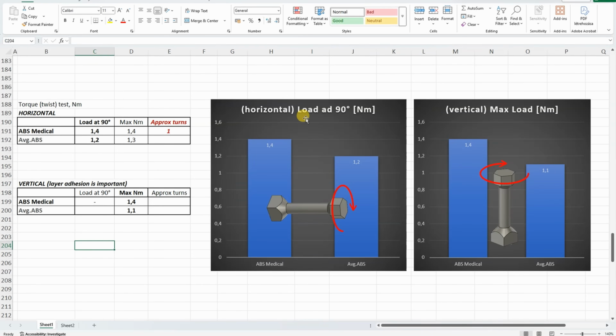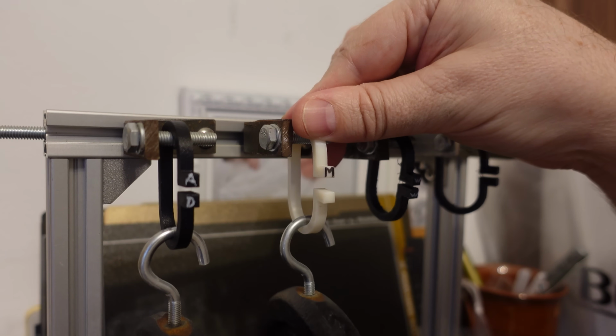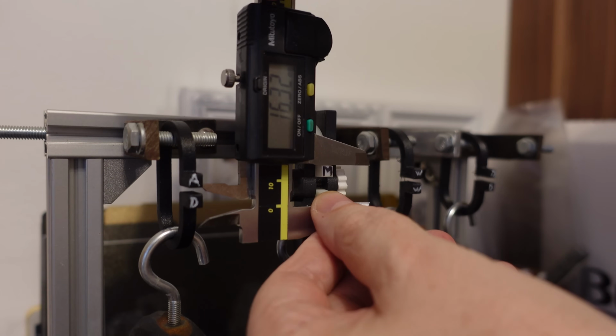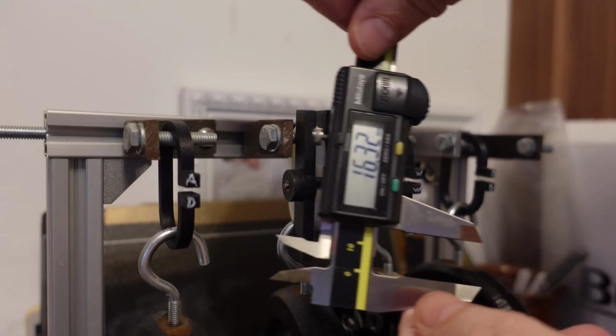Printed in horizontal position, loaded 90 degree rotation, small advantage on the side of the ABS Medical, and printed in vertical position, the maximal load is bigger again with the ABS Medical because of that better layer adhesion compared to the average ABS. Creep test, the deformation under constant load of 1.25 kilograms, 16.32.